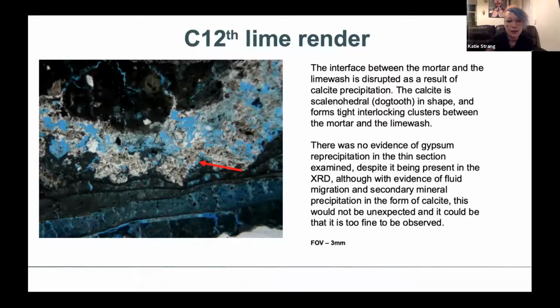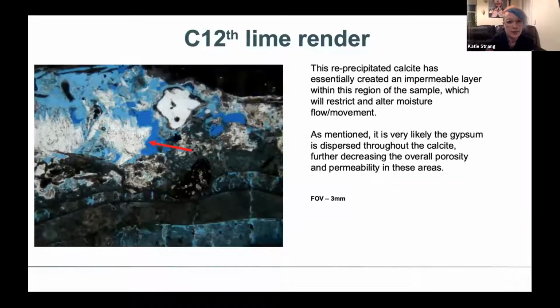So sometimes you will only see evidence of that in the XRD, or if you're looking under an SEM at the sample. And this is another image here just to show you the structure. It's essentially like dog-tooth calcite. So that's just the shape of the crystals. And they basically form quite tight interlocking bits in between that interface. And as I say, it just means that it creates this impermeable layer where the moisture is not easily able to transport through. And that's where you get a lot of problems with your outer surface and your paint.